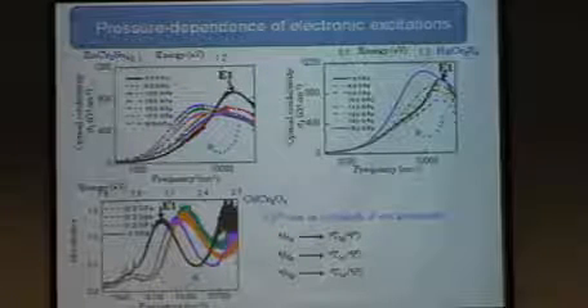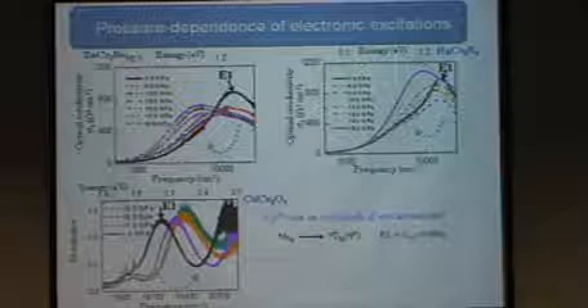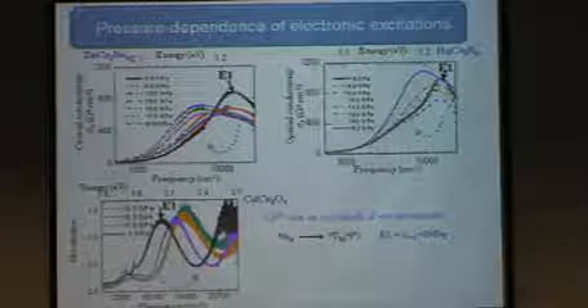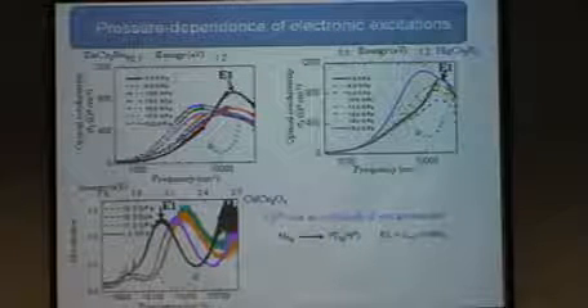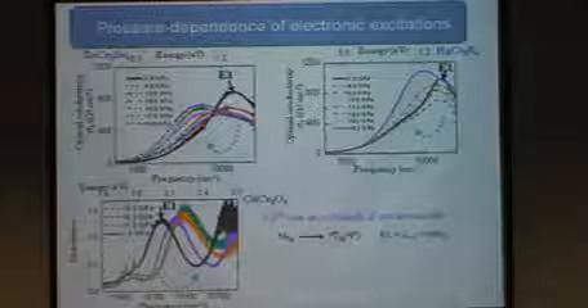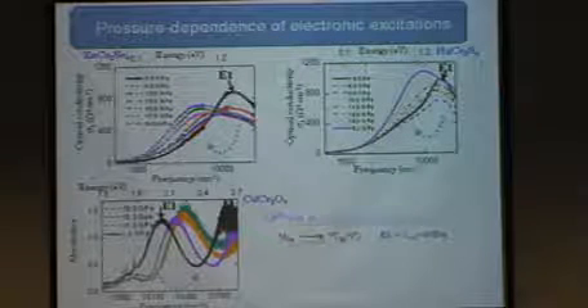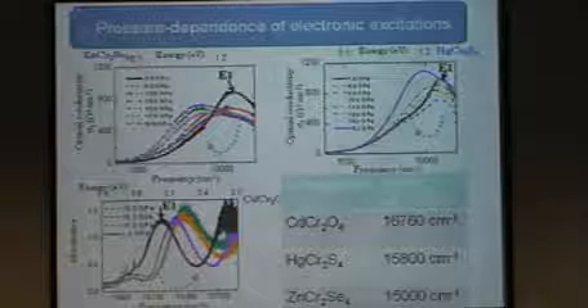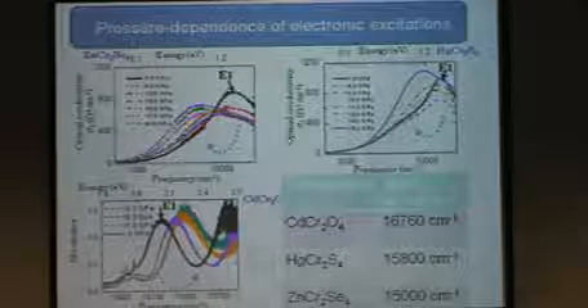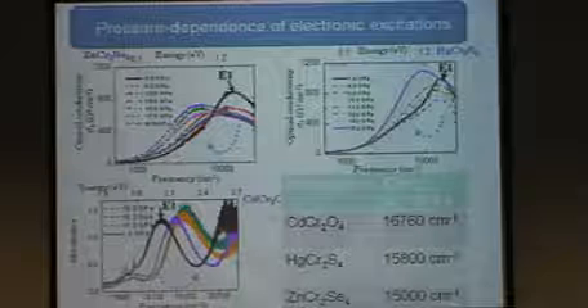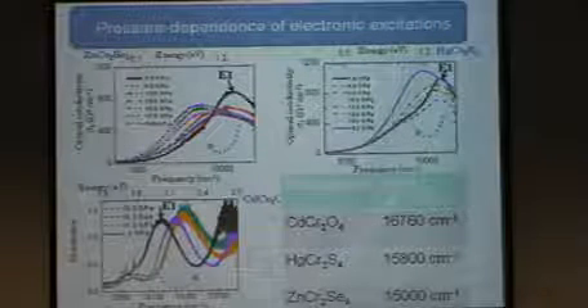For chromium ion in an octahedral environment, you have three spin-allowed d-d transitions. And the first d-d transition shows the splitting of the d orbitals in the octahedral crystal field. And so here, the E1 absorption band at low frequency tells that the splitting of the d orbitals in this compound is lower compared to the other compounds. So here I compare the E1 value for different compounds. You see for the oxide compound, it's higher compared to the other two compounds.